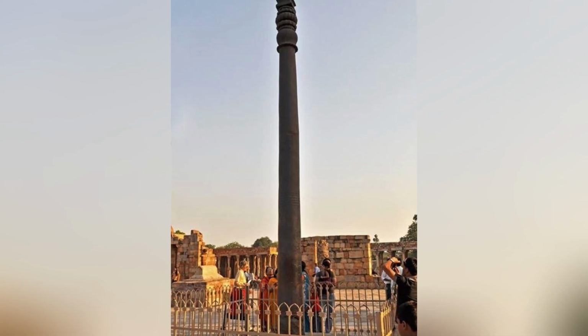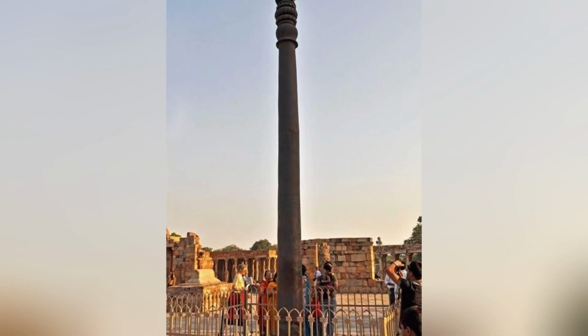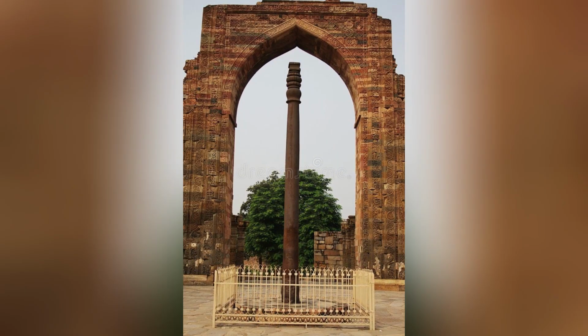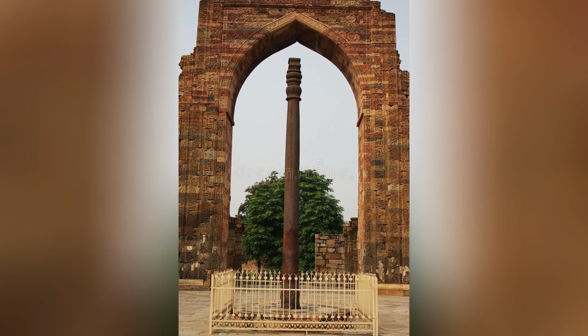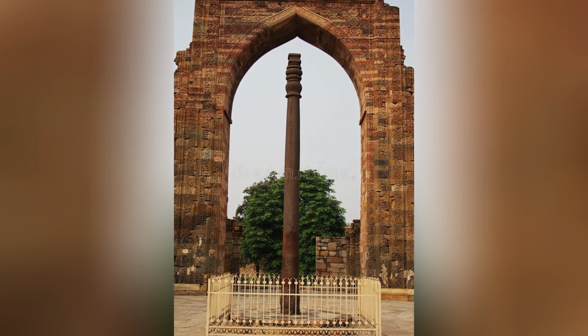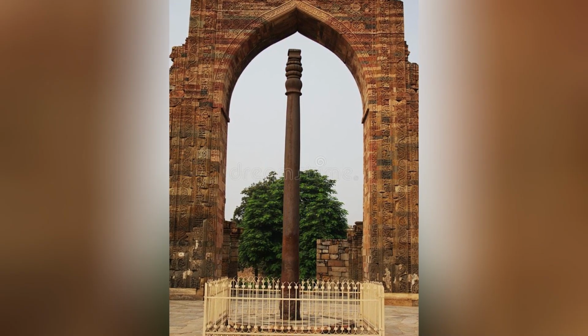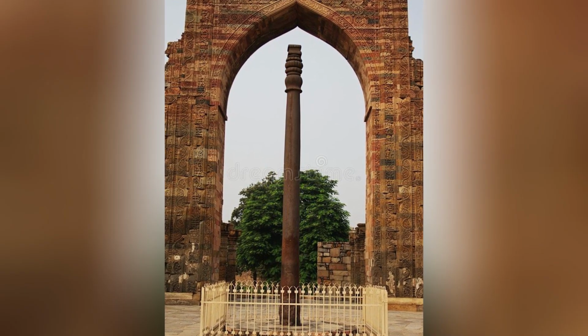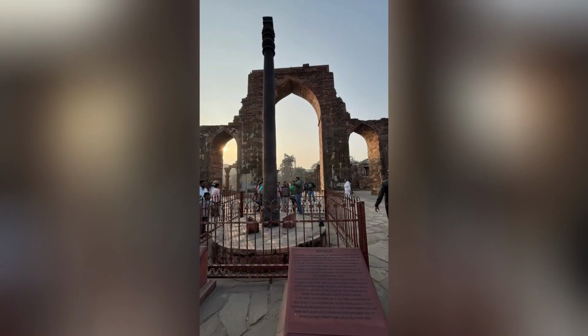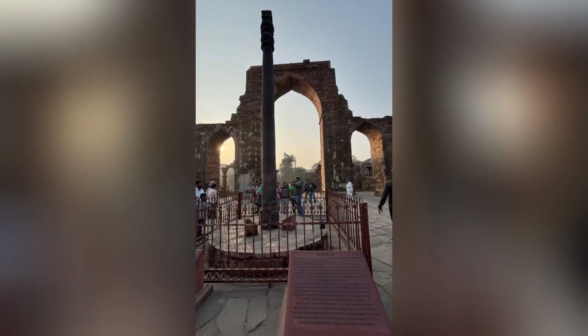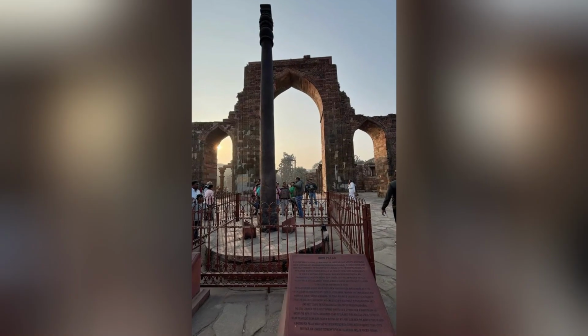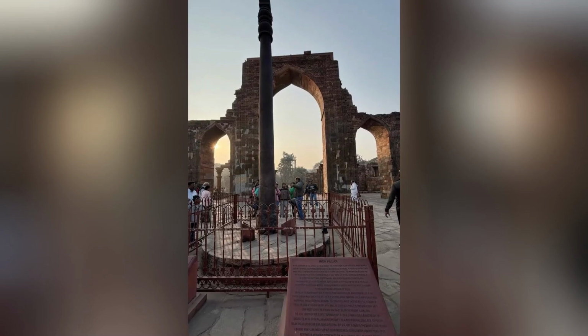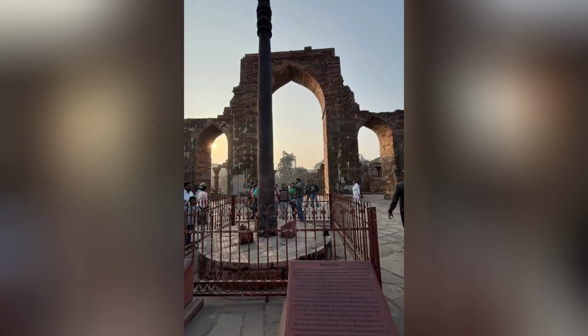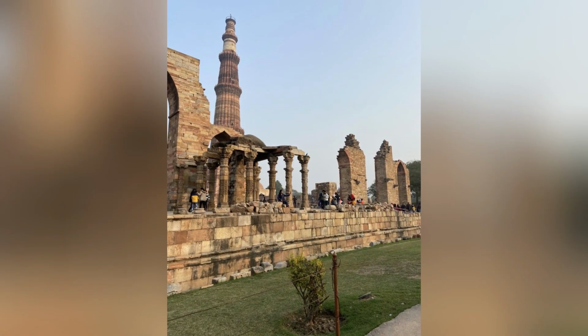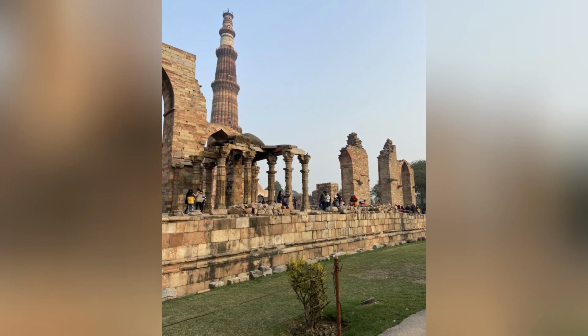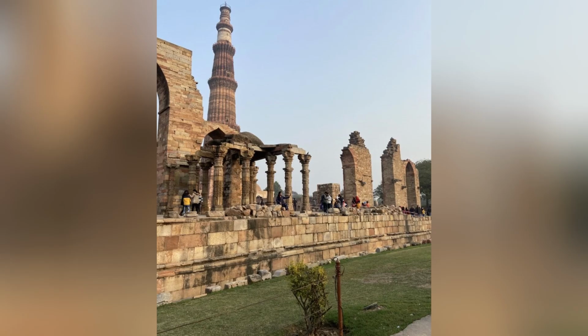The film is approximately 50 micrometers thick, roughly 1/20th of a millimeter, and it has been growing at an average rate of approximately 3/100ths of a micrometer per year, a rate that is negligibly slow compared to the corrosion rate of ordinary iron. The comparison between the corrosion rate of ordinary iron and the corrosion rate of the Delhi pillar is striking. Ordinary iron in the Delhi climate corrodes at a rate of approximately 50 to 100 micrometers per year.